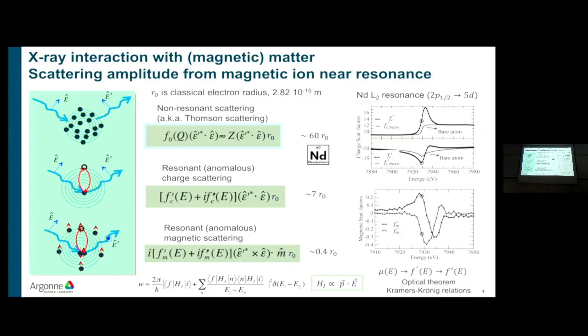and this denominator is what gives you this resonant enhancement. Believe it or not, these numbers, although very small, are much larger, orders of magnitude larger, than the interaction of the magnetic field with the spin of the electron. So the first term here is a first order process which is responsible for absorption. If you come in with X-rays and just excite an electron, that's your final state, and that's this first order process.